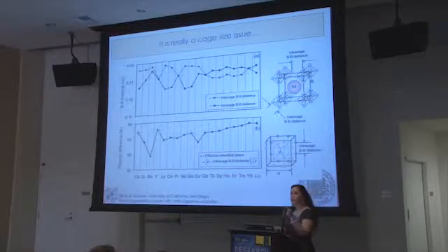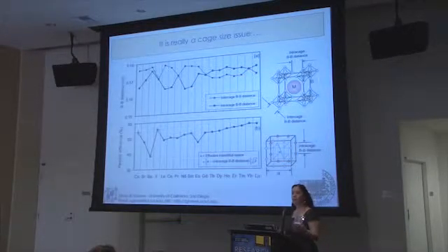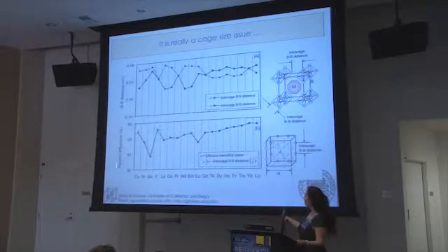What starts happening is that basically you have this rattling effect. The ion is not fixed really well inside the unit cell. There's rattling, and you basically lose stability. The whole crystal structure breaks up. And so it's an issue of percent difference between the space that you have inside, which is fixed, and the ion that you put inside that unit cell. For something where the difference in size is small, that means the ion is fitting quite well in there. Something like barium, that's highly stable.